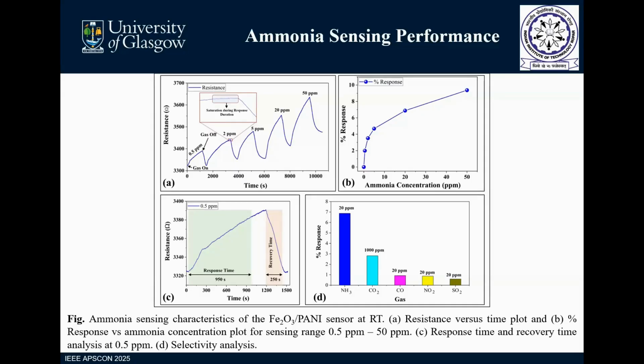Response time is generally the 90% change while moving from baseline to the saturation level of the inlet. Similarly, for recovery time, it is the decline from saturation to 10% of the total change. The selectivity of the sensor was also studied with respect to carbon dioxide, carbon monoxide, NO2, and SO2. These are some major analytes present along with NH3 in the environment, and we can see there is quite good selectivity for NH3 with respect to these other analytes present in the environment.